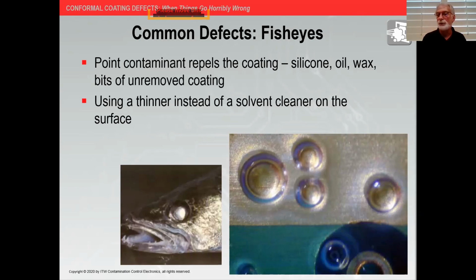If you're using water washable temporary solder masks, those are generally composed of either clay-based or cellulose-based material in an adhesive binder, a water-soluble adhesive binder. When it goes through the cleaning process, it's washed off, the binder's dissolved, releases either the clay or the cellulose, and then it goes where it goes, down the drain. But if you don't adequately clean it, now you've got little spots of clay, and these are very small particulate size of the clay or the cellulose. Those could be point contaminants. So I'm just pointing out that there's a variety of sources of this.